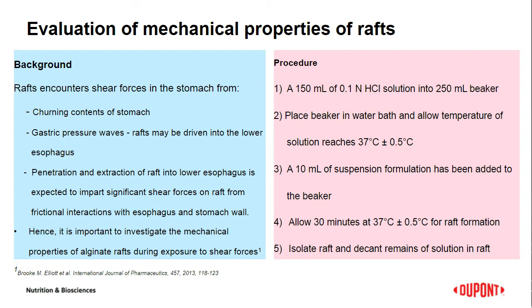So the evaluation of the raft mechanical properties is done by preparing the raft in 0.1 normal HCl, by adding 150 ml of 0.1 normal HCl into a 250 ml beaker and placing it in a water bath to attain a temperature of 36.5 to 37.5 degrees centigrade. Once the temperature of the solution is reached, the suspension formulation is added to the beaker and left for 30 minutes. Later, the raft is isolated from the solution and the remains of the solution are decanted. This isolated raft is used for further testing using the rheometer.